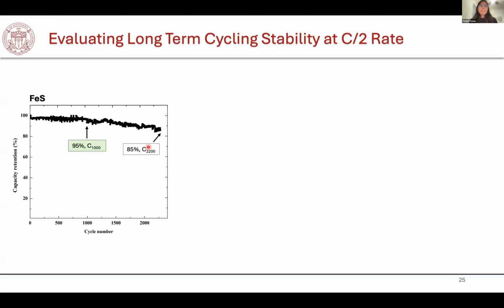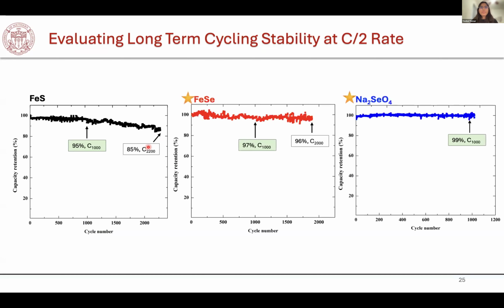So that's what's happening with this additive. But interestingly, when we introduced this selenium, we found very, very good results, extraordinary results. So even when the selenium is present in the electrode, the capacity retention at the 2000 cycle is around 96%, which is quite exciting. And this happens because the selenide is serving as an inexhaustible reserve of depassivating agent due to its electrochemical reversible nature.